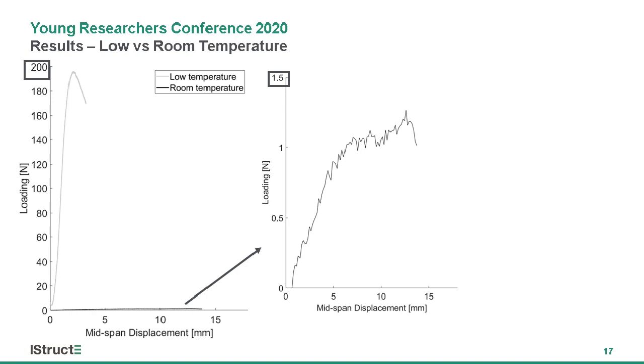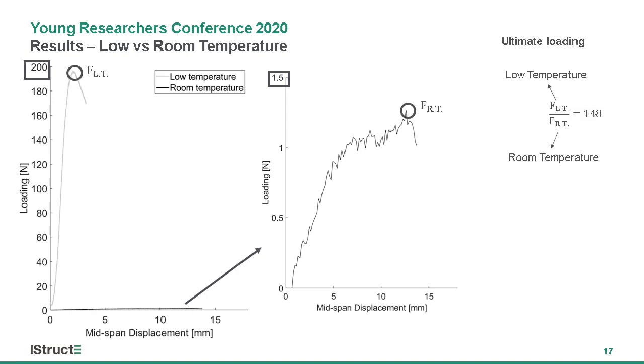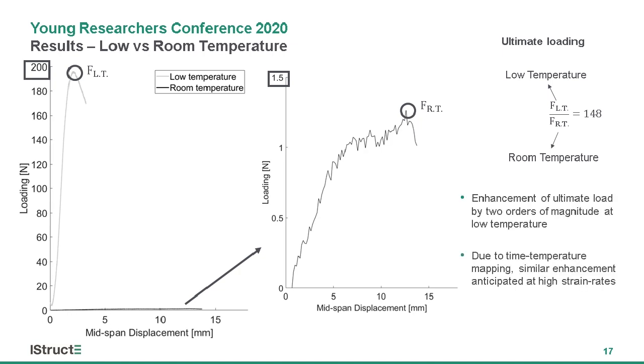This becomes more evident by replotting the room temperature results at a different scale. The results of the low temperature test demonstrate an enhancement of the ultimate load capacity of the fractured glass by two orders of magnitude compared to that at room temperature. This suggests an improved post-fracture bending moment capacity at low temperatures associated with a now stiffer interlayer working in tension and the glass fragments working in compression.